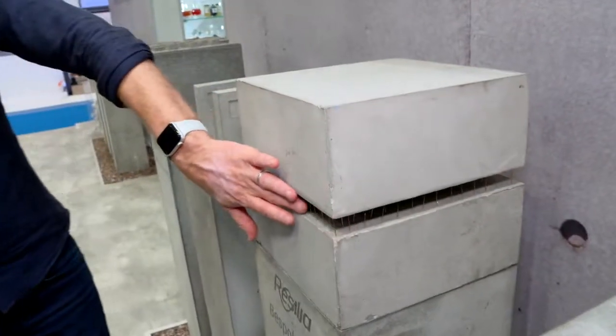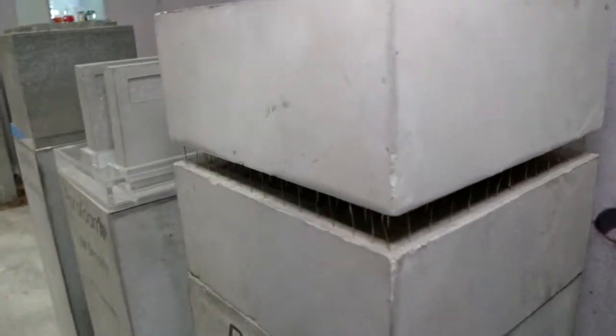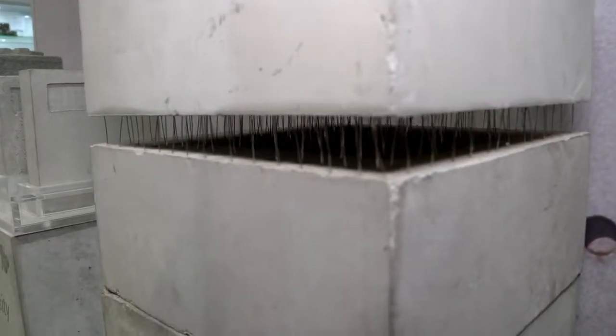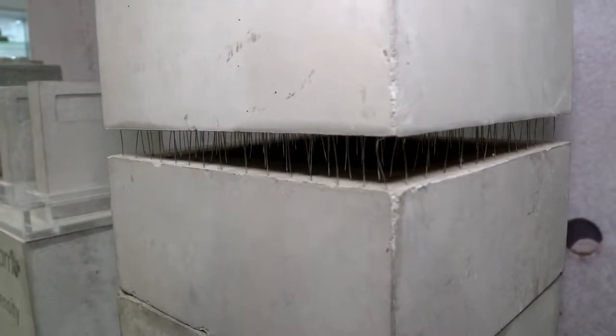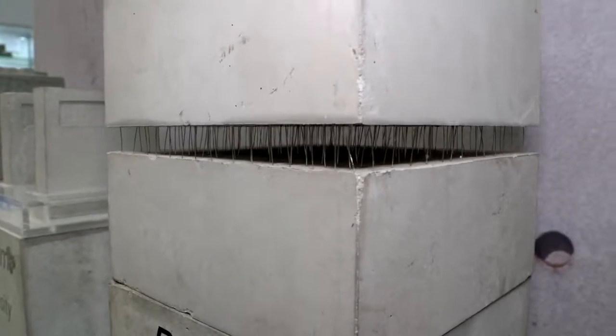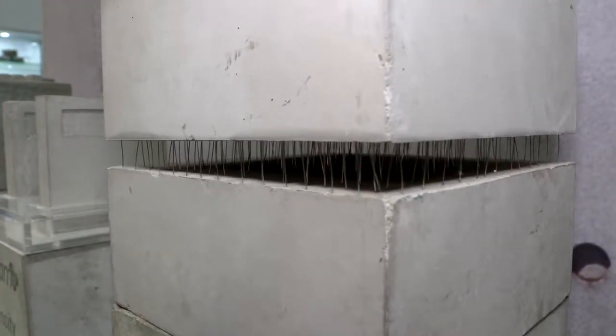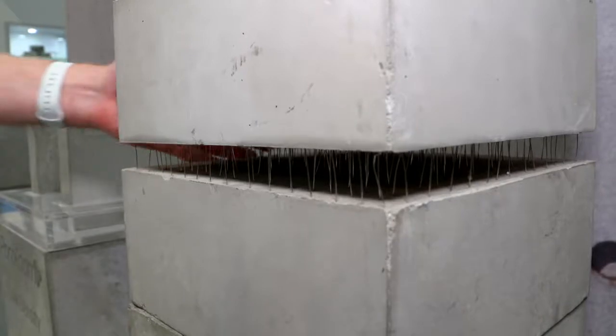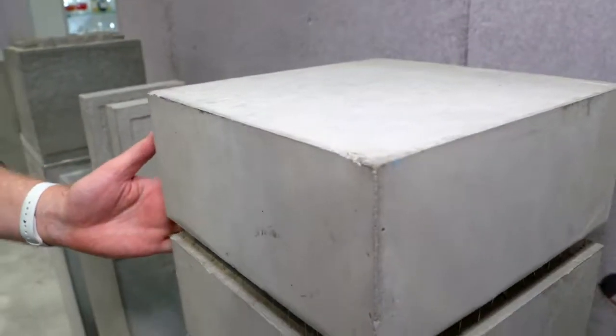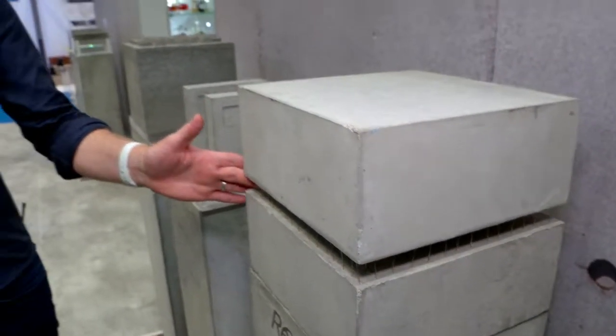I love this display here. Tell me what it is that we're looking at. Well, this to me is probably where the future of concrete and innovative concrete comes into play. It's bespoke high-strength concrete, so you can get concrete strengths of up to 120, 130 MPa at 56 days, and replace some of your steel reinforcement with a bespoke blend of fibre-reinforced steel and glass fibres.